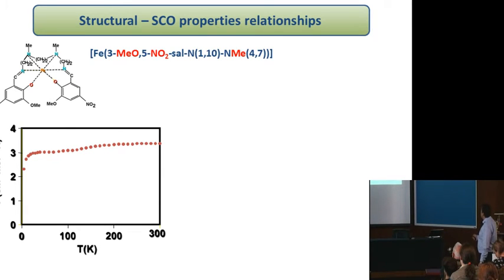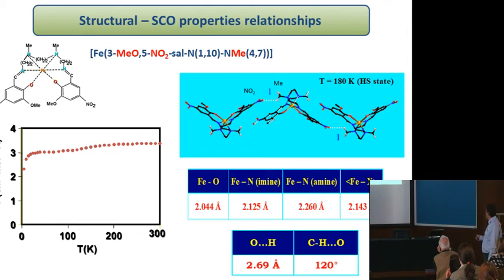Here we can see that the molecules are aligned along chains. And in this case, there is only one weak contact. It's a weak hydrogen interaction with a distance of 2.7. It's very weak, also with very small angles. So it's one very small contact between molecules. As a consequence, you have weak hydrogen bonds, and then you have a gradual and incomplete conversion. So we have a relationship between the structural property and the spin crossover properties. Here we can also observe the classical metal-ligand distance of 2.1 in the high spin state, here at 180 K.